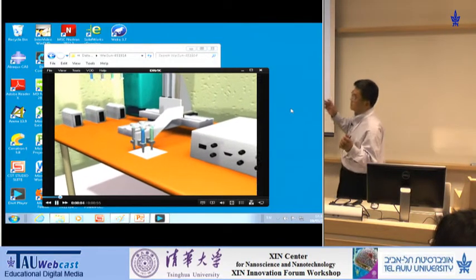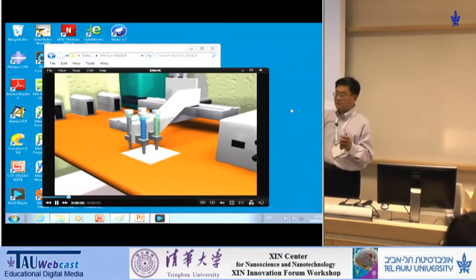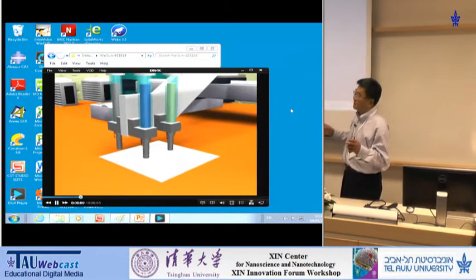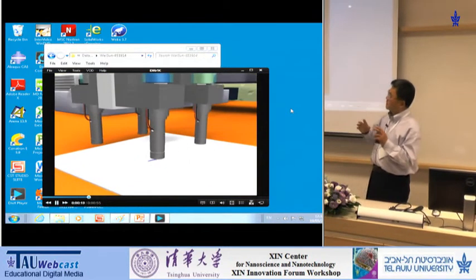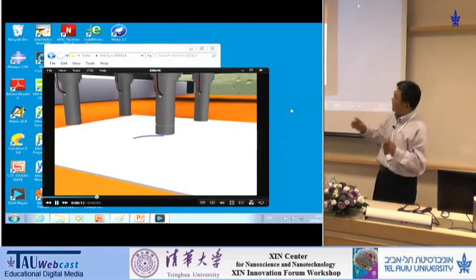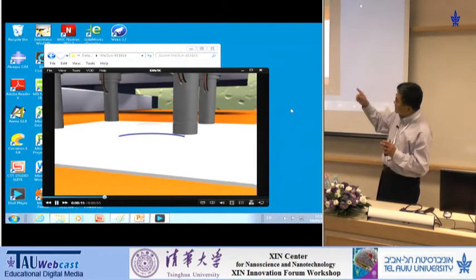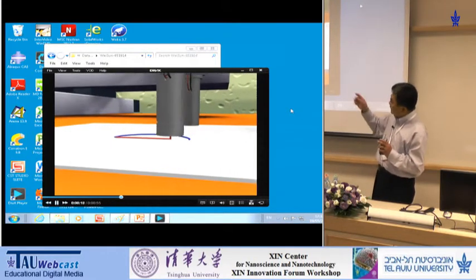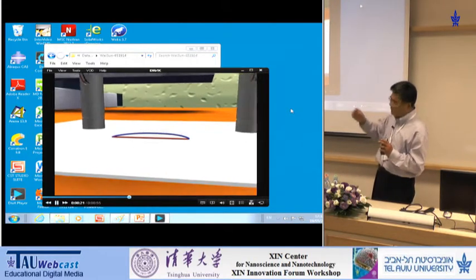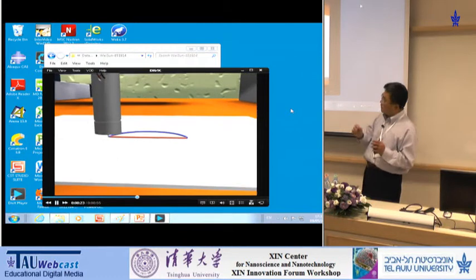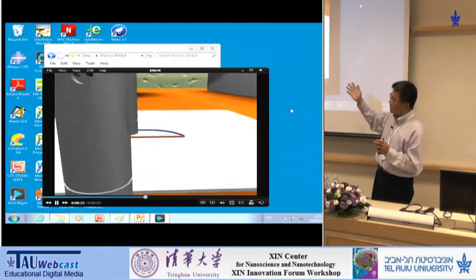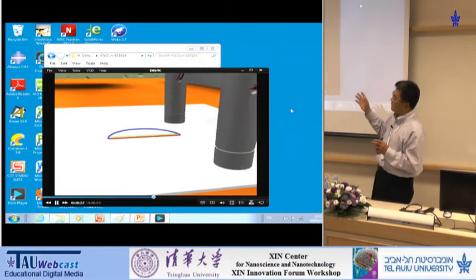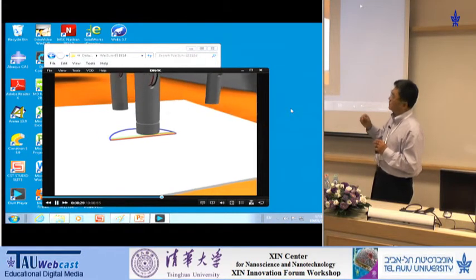What I'm trying to show you is that your printed cells have to be in a sterilized environment. You can think of this as a clean room or a hood. Then you have different nozzles. Those nozzles could be droplet if you want to print single cells, or continuous. The nozzle size could be 20 micron if you want single cell printing, or 250 or 500 micron if you want to drop a lot of cells and material.